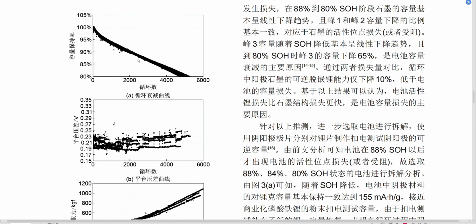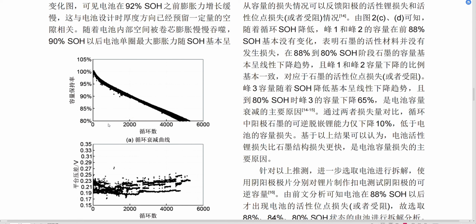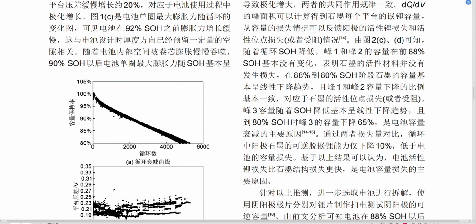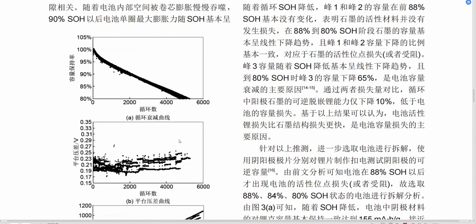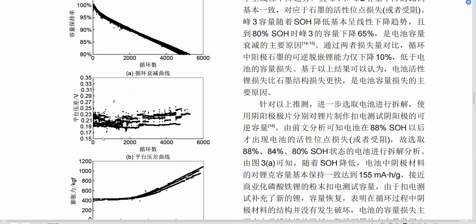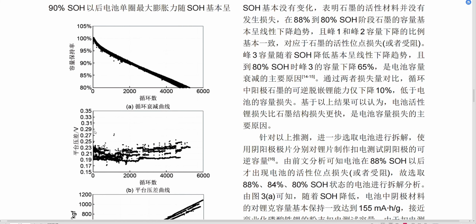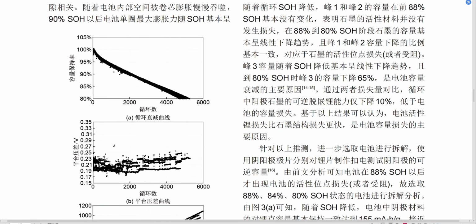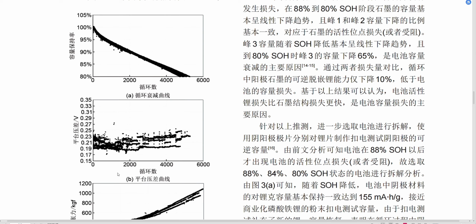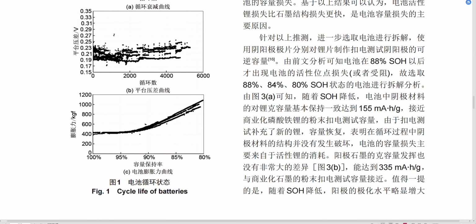In figure 1A, B, and C: figure 1A is the cycle number versus capacity retention. You will see it initially decreases faster, and when it reaches around 95%, it reaches a steady state with a slower decreasing rate. Figure 1B is the cycle number versus the average voltage difference. There are not many differences during the cycling.